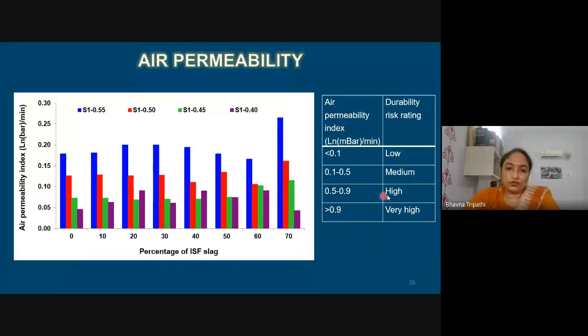So when we say the quality of concrete is good, let me compare all control mixes. All control mixes are having good quality, particularly the low water cement ratio mixes. These two mixes, which have water cement ratio of 0.45 and 0.40, perform better. And obviously, it is also known that we get better strength and better quality of concrete because the porosity is reduced.